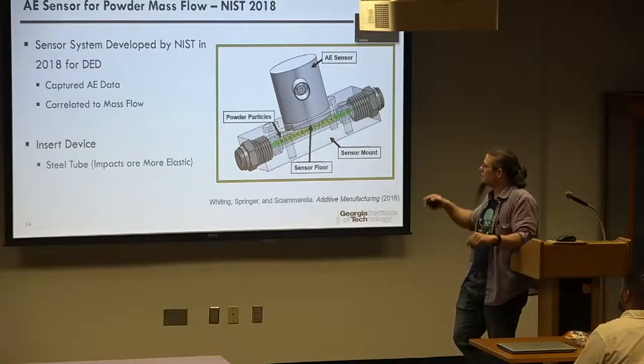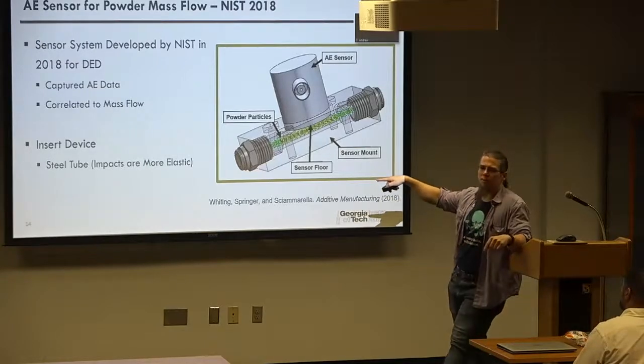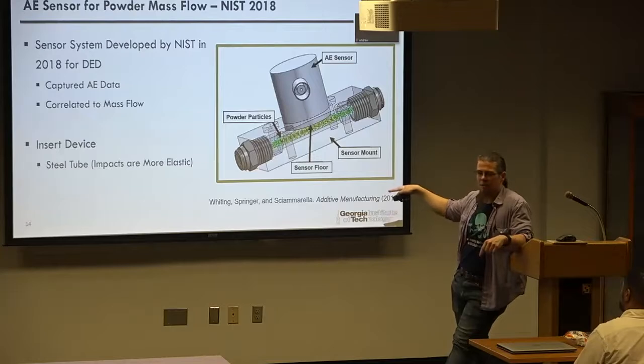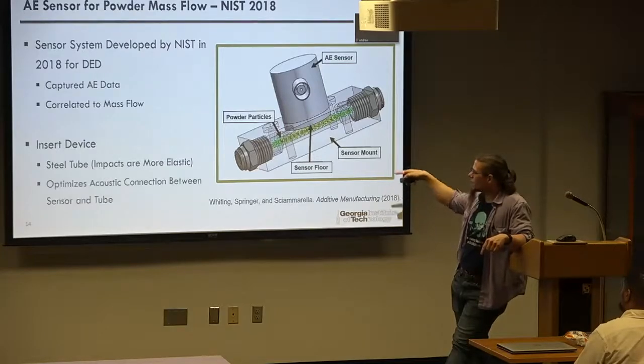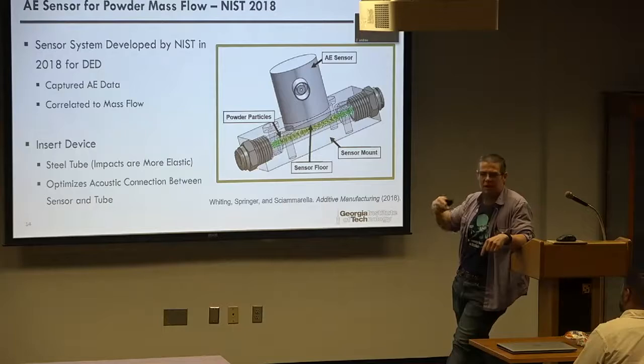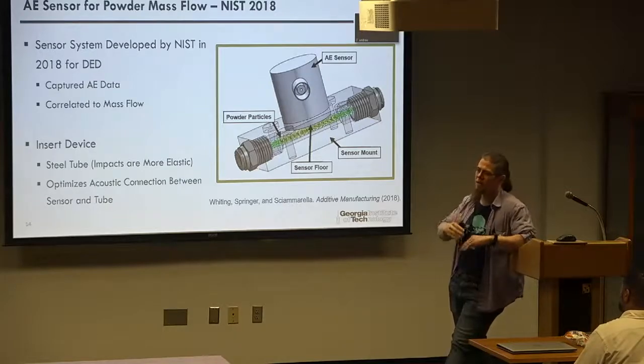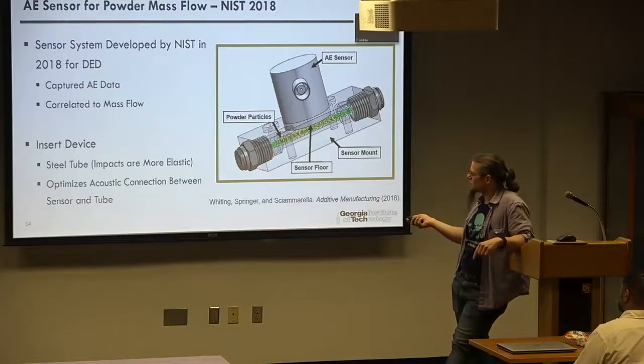The reason this is done is to introduce a steel tube, so the impacts are more elastic. So we're conserving a bit more of the energy, and we can optimize the acoustic connection between the sensor and the tube. So there's no real air gaps. There's no kind of bonding. We're just pressing that sensor up against the backside of the steel tube.